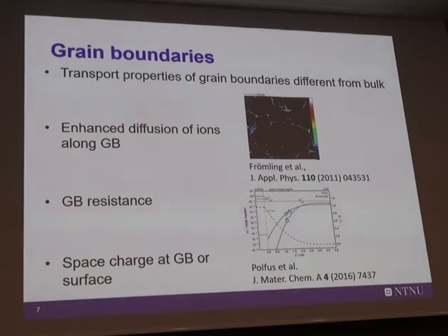In this case, it's protons which are trapped. This is a proton at the surface, and it is trapped at the surface, and it means that because of the high concentration of protons at the interface here, the transport across the interface is actually quite problematic. So the activation energy is higher. And here point defect modeling has been used in order to see how the concentration of the different defects changes as you go from the interface towards the interior. So this is due to the space charge related to the charge of the grain boundary.